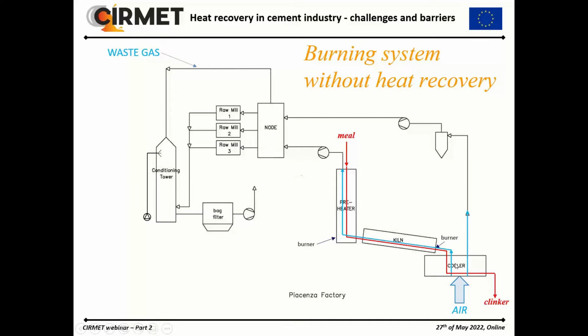The stream of the air is diverted in two branches. The first one passes through the kiln, the preheater, and gets to the node. The other one passes through cyclones and then reaches the node. In this node, we have gases at a temperature between 300 and 400 degrees, depending on the number of the cyclones in the preheater. Part of these hot gases are used to dry raw material in the raw mills, about 20% of these gases.